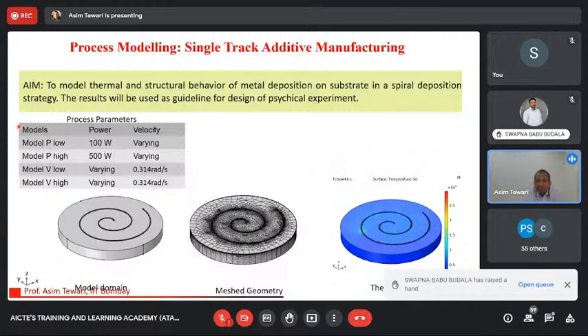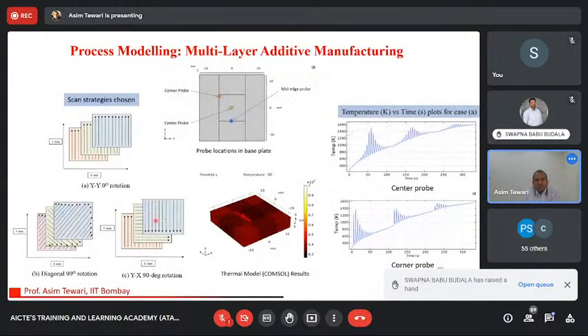that this, what we did for welding, is now being used for powder bed as well as directed energy deposition, additive manufacturing. And now the aim is to essentially have an entire model where we can change the power, we can change various build strategies and see how it is changing. So now this is to give you the hatching strategies. You could have all of them built layer by layer, each layer having the same direction, or you could have them rotated by 90 degrees. So you have one layer deposited like this, the other layer deposited like that. And you could have all sorts of combinations in which you could change the orientation of 90 degree also. So you have it deposited like this, then like this, then like this, and then like this.